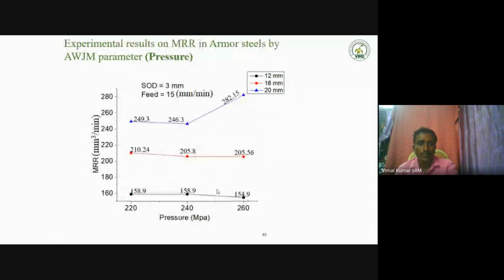So here also, traverse speed influences the material removal rate. Next, pressure and its influence on the material removal rate. Here we increase the pressure. It is mostly not a reason behind the material removal rate, because here we mostly receive a straight line for the 12 mm and 16 mm thickness plates. For 20 mm thickness, the pressure does influence material removal rate, because a higher volume of material is involved at a particular pressure. But at the lower thickness levels, pressure is not influencing material removal rate as per our experimental study.